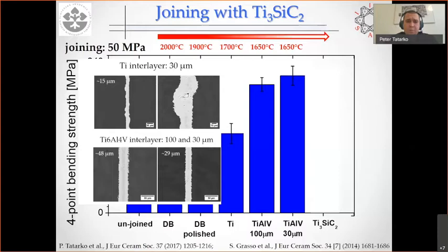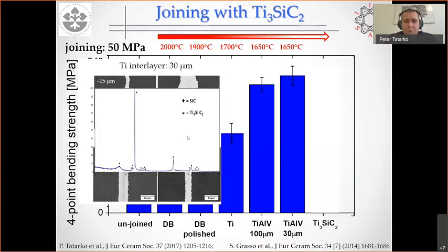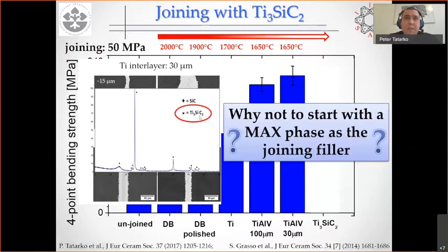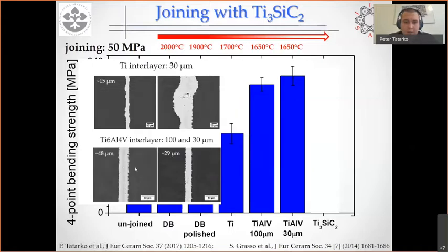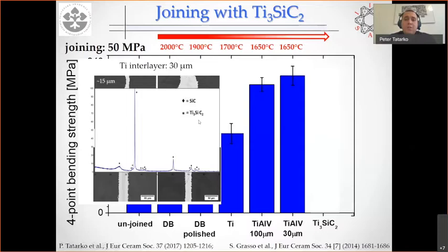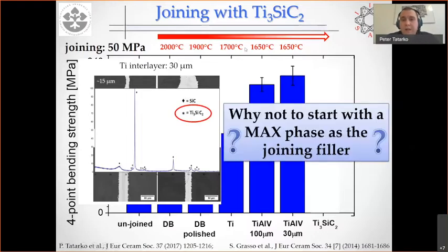One important point, when we did the XRD after the joining, we found, of course, silicon carbide from the matrix, but we found titanium silicon carbide, the so-called MAX phase. So in other words, this joining interlayer was formed by the MAX phase titanium silicon carbide. So the question was, why use titanium at 1700 and then end up with a MAX phase if you can use the MAX phase directly as a joining filler? So that was our motivation to use the MAX phase as the joining filler.